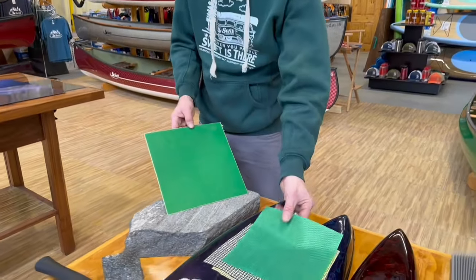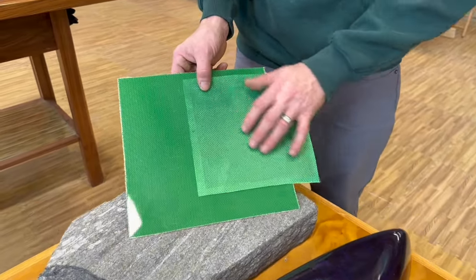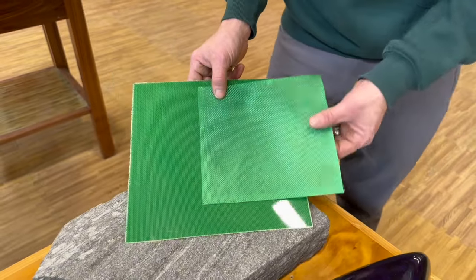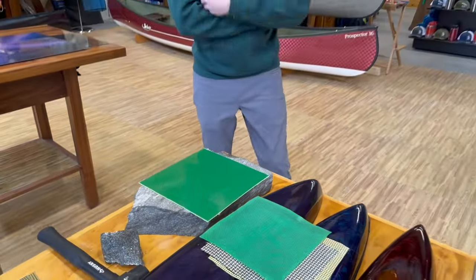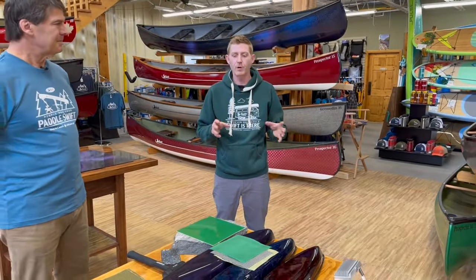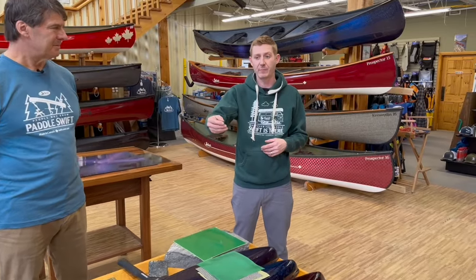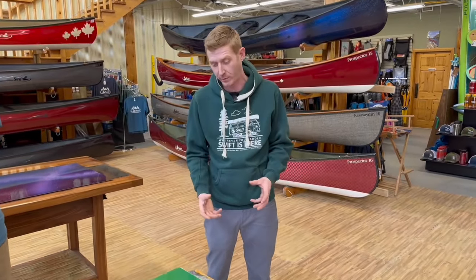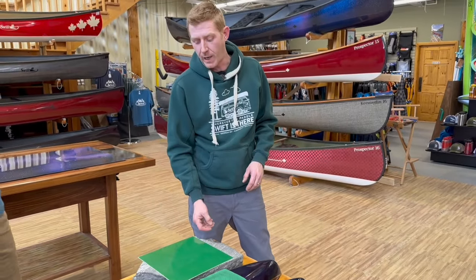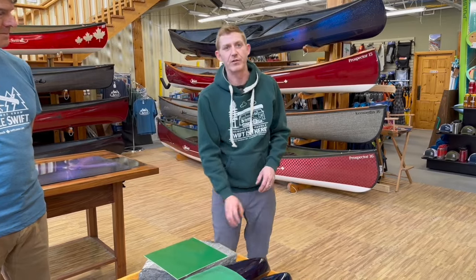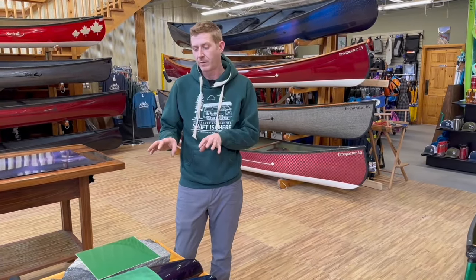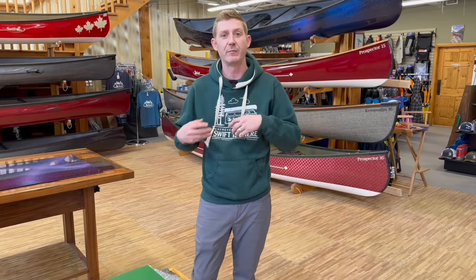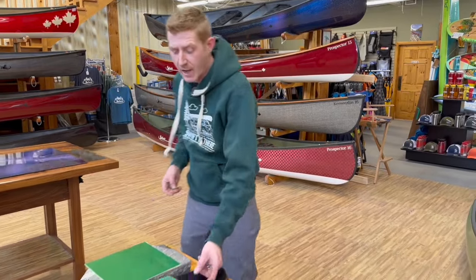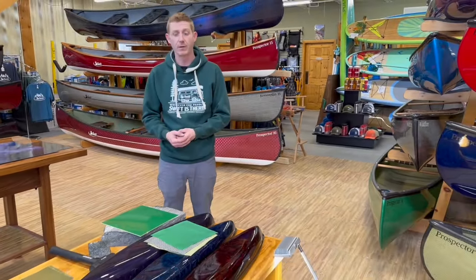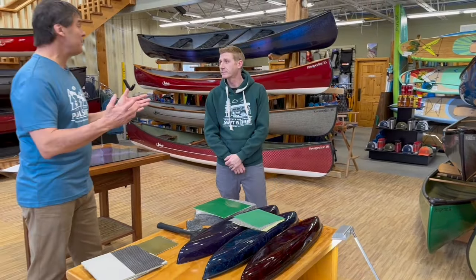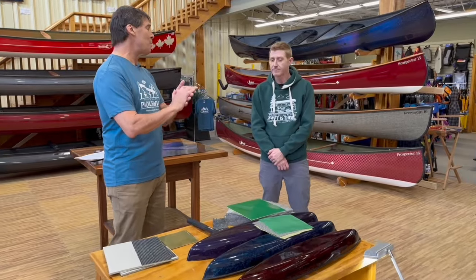And what a lot of people don't realize is the finish that you're seeing, the color that we're getting, is actually from the material itself. It's not in the coating. So in our process, over the years, gel coat has not really changed much. In order for it to work properly and cure properly in mold, it actually has to be sprayed quite thick in order to perform properly. So this was a big reason why we worked with the company that develops UV Shield, so that we could spray the thinnest amount of coating in mold to save weight, and give better flexibility and better impact resistance. And as a result, we're getting much more durable, much lighter canoes.